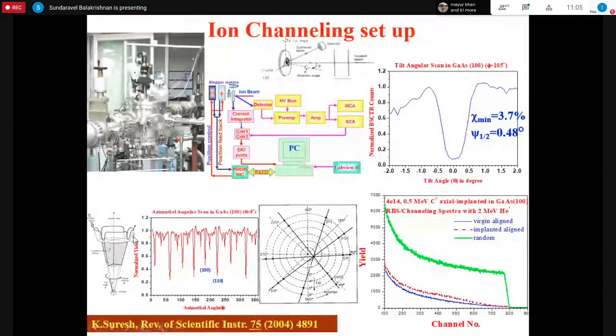Our tilt angle is 5 degrees. We are turning the sample from 0 to 360 degrees, and we find the yield of this gallium plus arsenic signal on this high energy side. We take the high energy side because there the reduction is greater, and we get this sort of dips from 0 to 360 degrees. And then these dip positions, for example, here phi value is something close to 15 degrees or so.